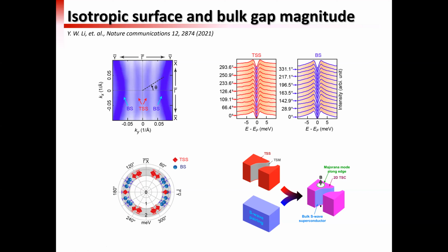I think so far this is the clearest gap opening below Tc that we can see in any topological superconductor candidates. And also this material is relatively stable and it's stoichiometric. So we hope that the colleagues in transport can find use of it.